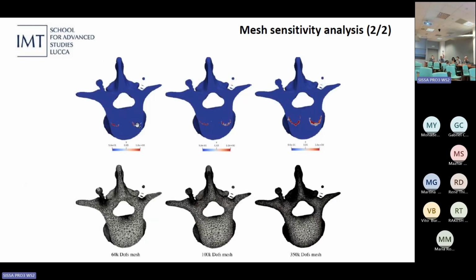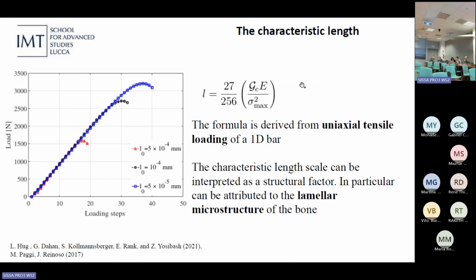Here we can see a convergence in terms of profiles of the damage at the fixed loading step. We can see that basically if we cut, we can see the convergence of the damage profile in a semicircular region around the end of the screws inside the cortical part of the bone.